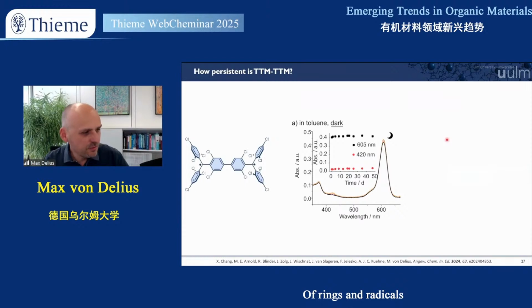And finally, maybe one thing I want to point out is the stability. So we took some time studying the persistence, I should maybe say. So how persistent is this kind of Chichibabin radical really? And it turned out really, really persistent in the dark. So this is 50 days, almost no drop in the UV-vis spectrum. And we will clearly see any degradation here in the UV-vis. So in the dark, you can really trust this molecule to be persistent. And this is in solution under air with moisture. So these are really bench conditions except for the missing light.